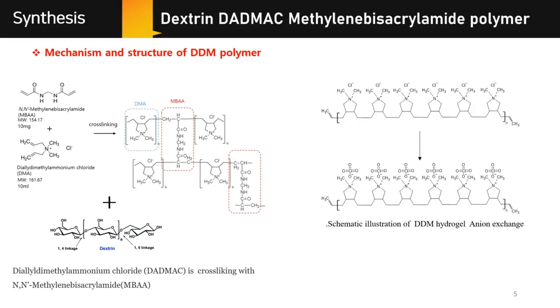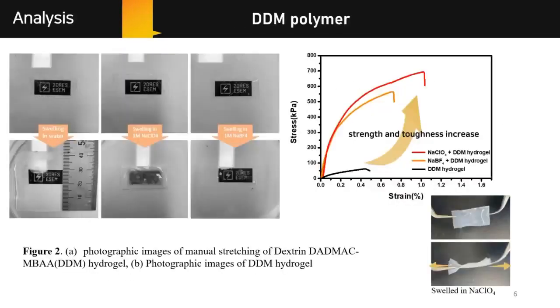DADMAC monomer is in aqueous solution, and it is cross-linked with MBAA. The second network is dextrin polymer, and its polymer chain has a high molecular weight. One of the characteristics of DDM hydrogel is that the Cl- anion of the polymer has an ion exchange reaction with salts containing anions like ClO4- or BF4-.